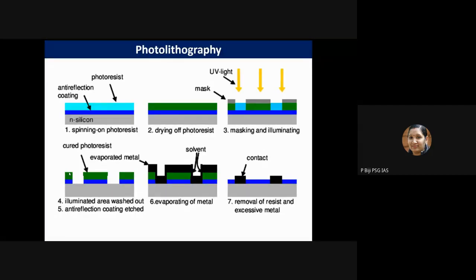In this case, you need a photoresist, and it will be exposed to UV light with a desired photo mask. Some parts of the photoresist will be hardened, and the other parts you can etch out using wet etching or some other physical etching process. Then you can evaporate your metal, and after that you can wash out the resin which is present as residual material.